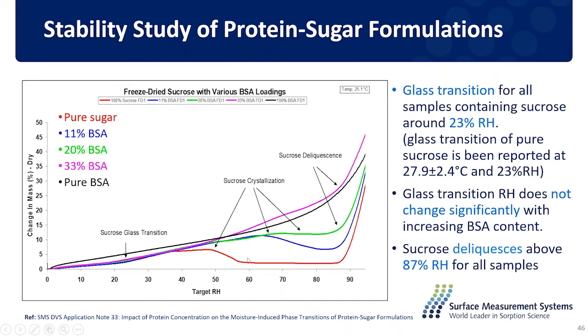So there are three very clear transformations, the vapor-induced phase changes happening with the moisture sorption. At the low end, we have the glass transition of this sugar sample, which is about 23% RH, quite consistent with the literature reported value for the sugar sample. And we also have the crystallization point for the pure sugar sample at about 50%, and with increasing concentration of the protein, there is a higher relative humidity for the crystallization. And then at higher humidity, the sample will go to the deliquescence point.